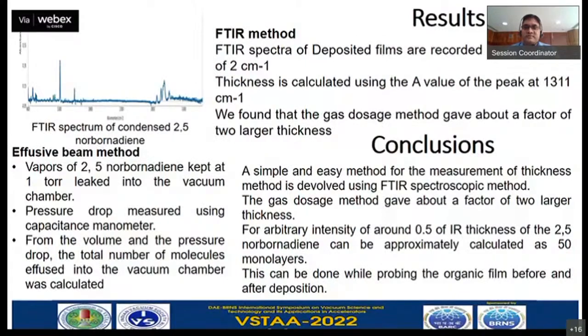Next slide, please. These are the results. This is for one deposition of 2,5 norbornadiene at around 15 Kelvin and 10⁻⁷ millibar pressure. Then the thickness is calculated using the A value of the peak at 1311 cm⁻¹. And we have calibrated using the effusive beam method, and we found that the gas dosage method gave about a factor of 2 larger thickness. And so this is very easy method for us, Madam, because your time is over now.